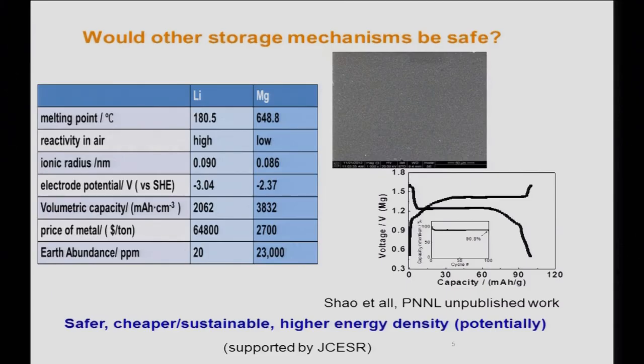Now, in addition to lithium chemistry, we can look at other chemistries that are intrinsically safer. One example I'm giving here is the magnesium battery, which is what Dave works on. Magnesium has two electrons and can get you to high specific energy density, and it's more abundant, all those things. However, another very important issue, again partially supported by JCESR right now, is that magnesium, for whatever reason, is fundamentally different from lithium. We have developed a few generations of electrolyte and electrode material for this chemistry. If you look at the surface, it doesn't form dendrites on the magnesium. You always end up with a very, very smooth surface. So those are the two examples I wanted to give to intrinsically make the battery much safer for transportation applications.